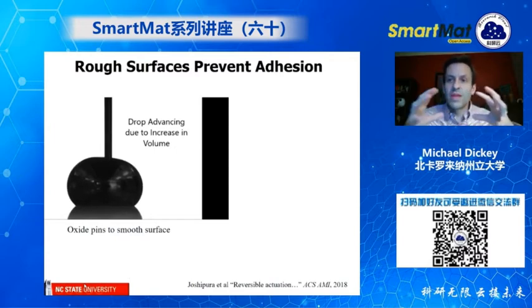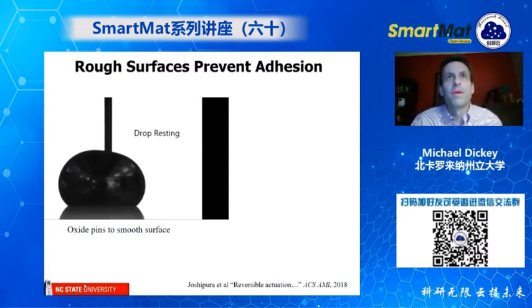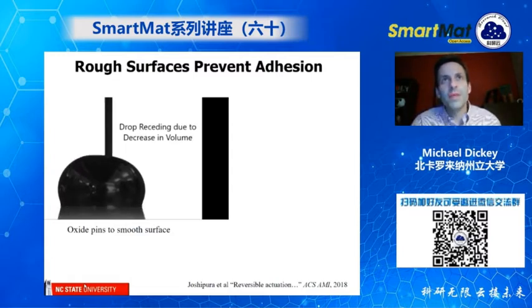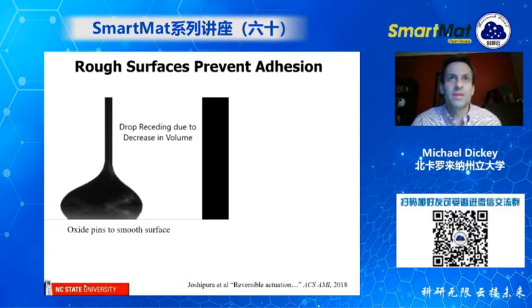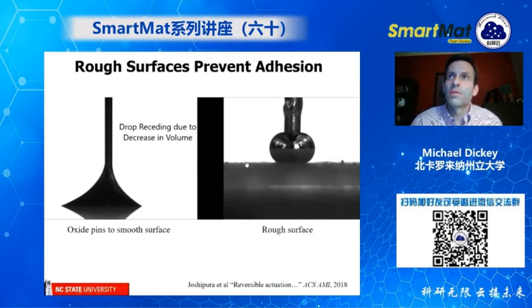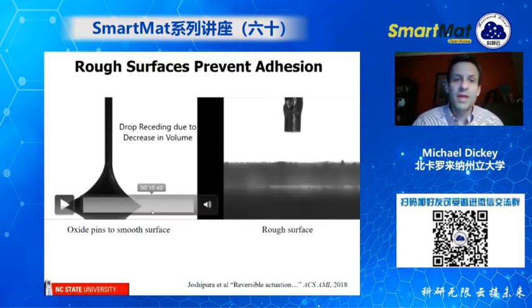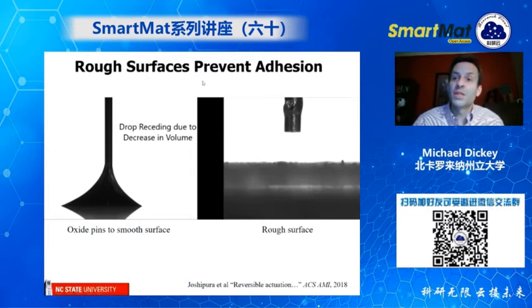So to illustrate this, this is a droplet of the liquid metal, and if you inflate the droplet, it's called advancing, you basically make the droplet bigger, and then you suck the liquid back into the syringe, you'll see that the droplet gets stuck. It stays stuck to the surface. So you see it's pinned here on the edges. Now, if you put the metal on a rough surface, you can spread it out and then pull the metal back into the syringe, and it doesn't stick. So this key idea is that rough surfaces prevent adhesion.